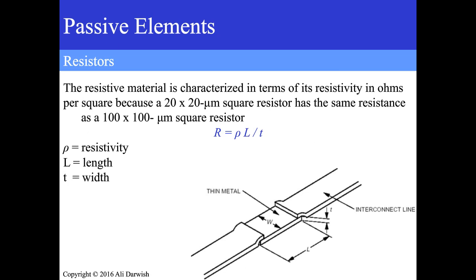For resistors in general, we evaluate the resistance by looking at how many squares we have. So we look at the width and the length. And so a 20 by 20 micron square will have the same resistance as 100 by 100. Of course, even though they have the same resistance, they have different ability to handle power. The larger resistor will be able to handle much more power than the smaller resistor. And that's an important point that I'm going to get into next, which is current limits. And this is something that is critical when designing MMICs.